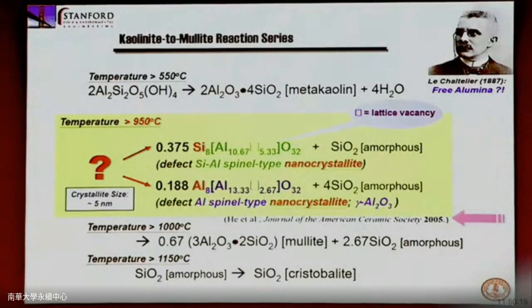I don't want to go too much into the detail, but I'm just trying to say, in terms of clay burning, you find a lot of positive and negative opinion. Some people say it's very effective, some people say it's not, and we find out it's because a lot of people actually do a lot of mechanism. One of the mechanisms that we find out is the kaolinite-to-mullite reaction series, very important, that you can have the mineral phase to host your heavy metal. Whether you're being hosted nicely or not makes huge differences.